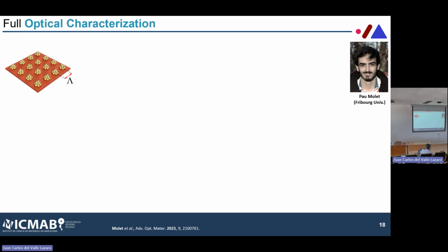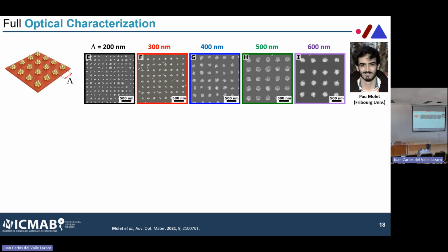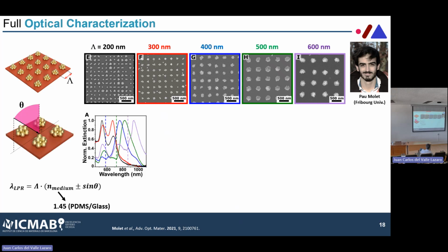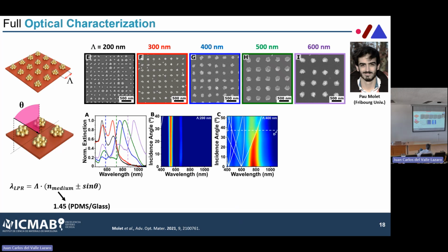And so how can we try to understand how we can make this narrow? And this is, by the time I arrived in ICMA, basically what we started looking into. So the first thing we did was, okay, let's take this nanoparticle, let's make different lattices, and let's look at what we get. And so again, this is the optical response that we got. We were not very happy about it, but then we decided to do a full optical characterization, because this is only with your sample illuminated from normal incidence. So now we tune the angle.